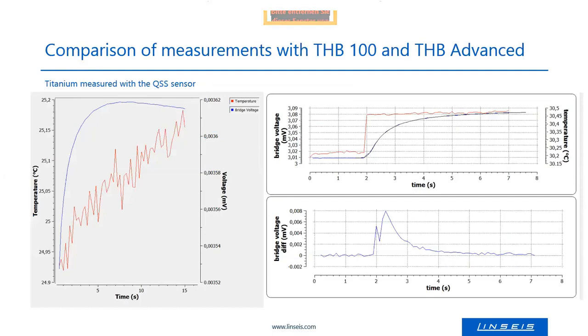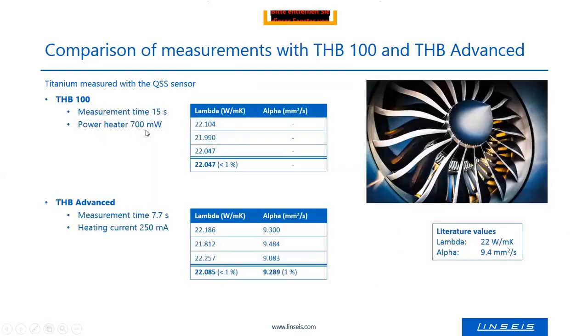Then the next example shows titanium, which is a metal at the lower end of the thermal conductivity range. The measurement looks a little bit more noisy because the signals are getting smaller, the higher the conductivity is. And when we calculate the data, we fail for the THB-100 to get the alpha, the thermal diffusivity. It's not possible because the experiment is already too fast for that device. But lambda can be measured accurately. So for lambda, the older instruments are quite okay.